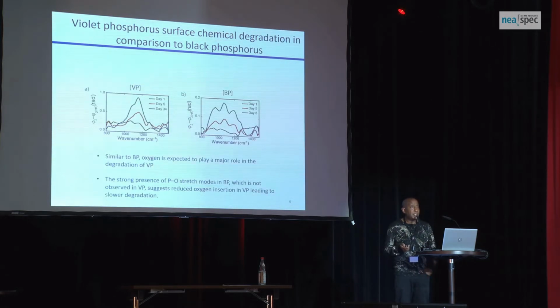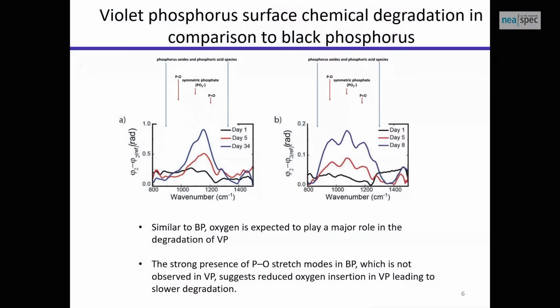If you now do the same kind of spectroscopy on these bubbles and compare the two, and literally superimpose your assignment for black phosphorus on violet phosphorus, what you notice is something interesting. You see that the spectra is narrower in violet phosphorus compared to black phosphorus, and that comes from this PO stretch mode missing, a certain portion of it missing here.